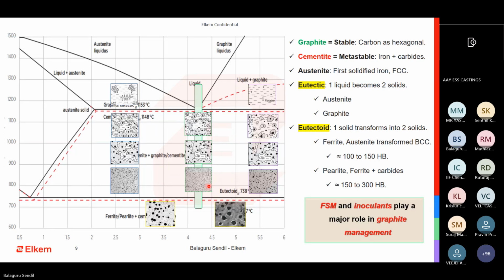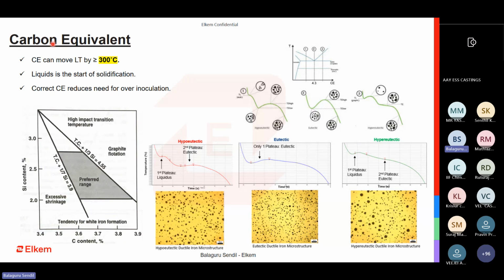As I told earlier, carbon equivalent is very, very important when it comes to casting yield optimization, because the carbon equivalent can move the liquidus temperature by up to 300 degrees Celsius. What I mean by that is that when the metal begins to solidify, it can go either above 300 or below 300 degrees Celsius. So it plays a very vital role. Correct carbon equivalent also reduces the need for over inoculation, because I have heard people saying that they need to add minimum 0.5, 0.6 of inoculant, otherwise they are not getting mechanical properties. Sometimes I wonder, it is good for us, we sell more inoculant, but it is not a required process. Is it because of the inoculating elements, or just because of the silicon, or some other elements that come with the inoculant, that they are preferring it? We need to understand this. Overdoing is not always ideal.